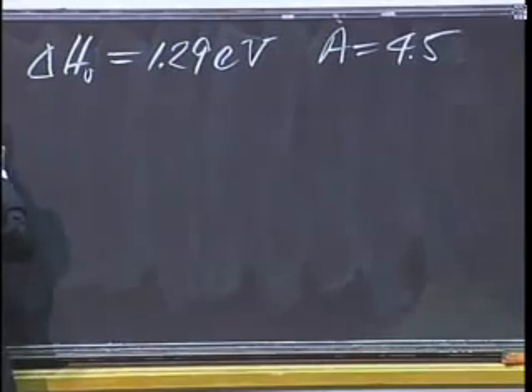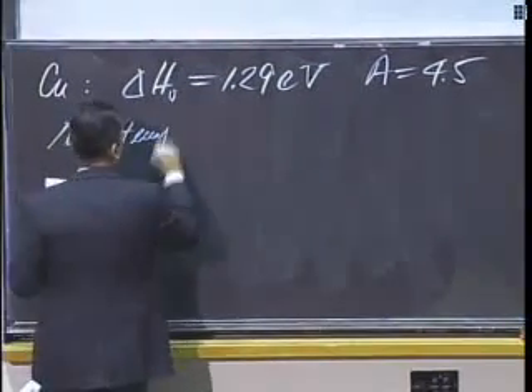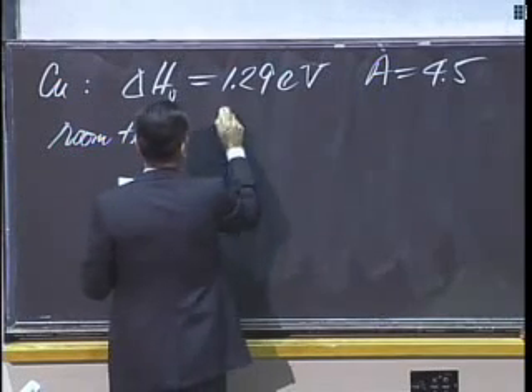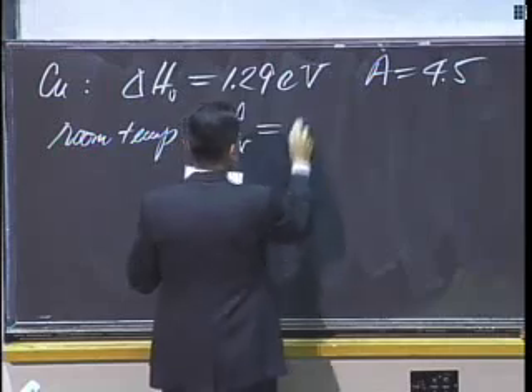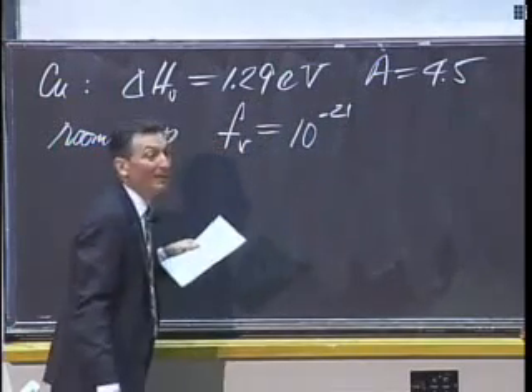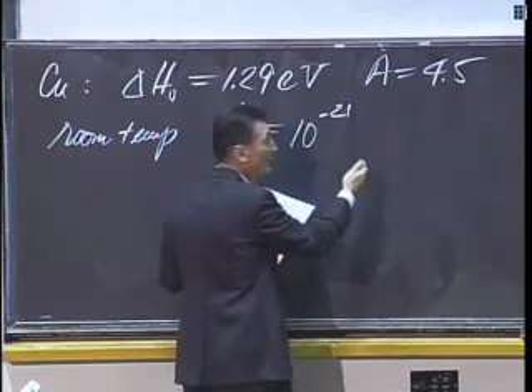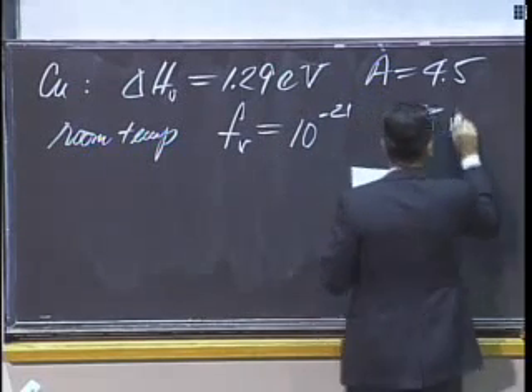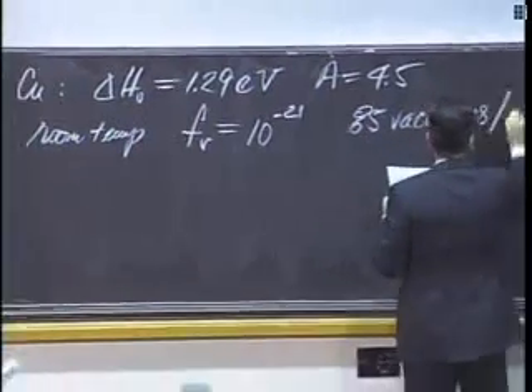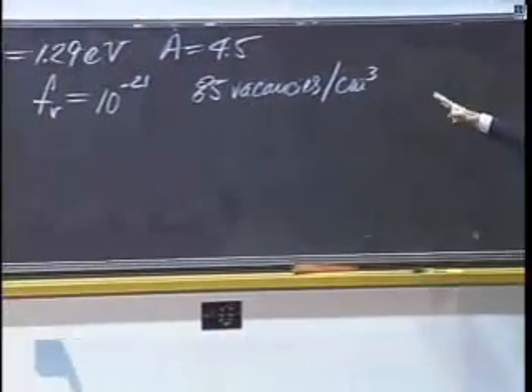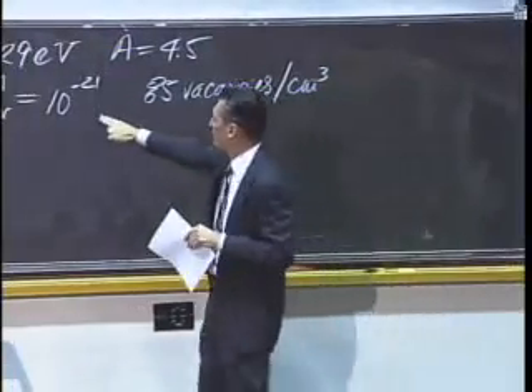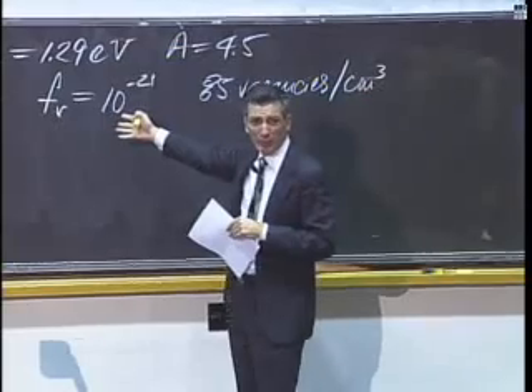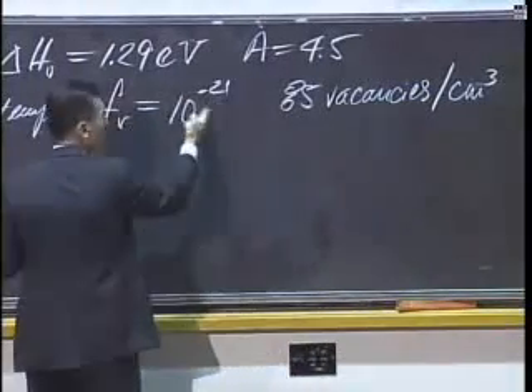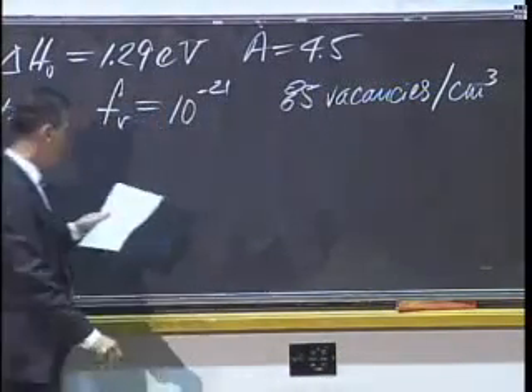So I said, okay, let's look at room temperature. At room temperature, I plugged these numbers in, and I got the fraction of vacant sites as 10 to the minus 21. Well, if you multiply by the density of copper, that turns out to be 85 vacancies per cubic centimeter. I mean, this is vanishingly small. This is almost none, right? Because we have a roughly Avogadro's number of atoms per cubic centimeter for condensed matter. So this is really, really low. And 10 to the 21, 10 to the 23, there's 100 difference, and sure enough, there it is. 85. There's so few you could give each of them a name.